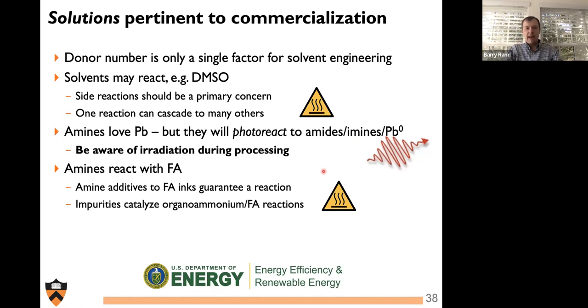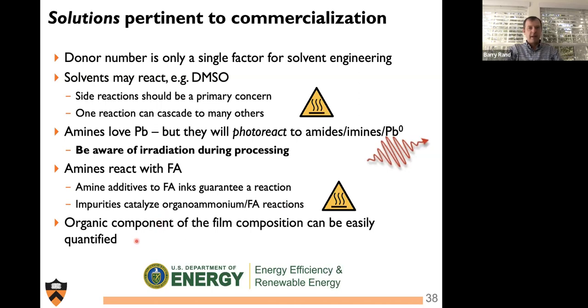Amines also will react with formamidinium. And so adding amines to any formamidinium containing ink guarantees a reaction. There's no other way to put it. But also, and a bit more subtly, impurities, for example, things like lead acetate or lead oxide, will catalyze these reactions because they lead to deprotonation of the organoammonium salt. And that, we can quantify, and I think we should start to quantify the composition of our film through NMR analysis.